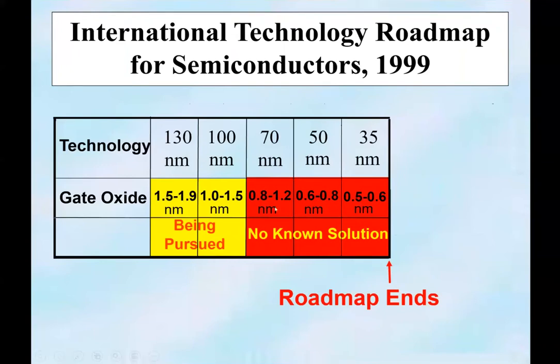This second row actually was not incorrect. We cannot make the gate oxide infinitely thin. And in fact, if you look at the equivalent oxide thickness, EOT, even today, we are not getting this thing. 0.7 nanometer is what we're using, EOT, including the high K. So that part is not wrong. But what's wrong is that it says we cannot turn off the transistor if we don't scale the oxide thickness.